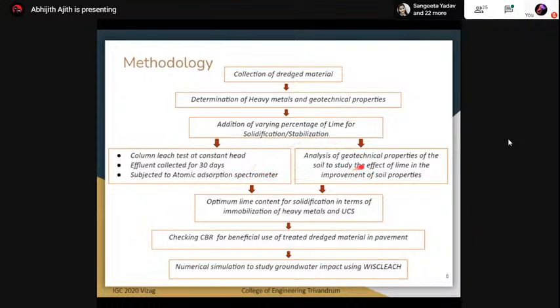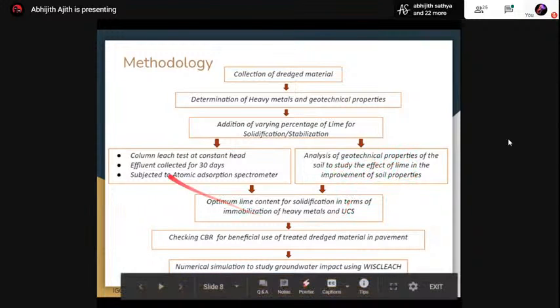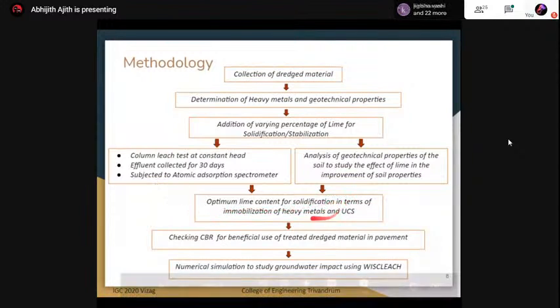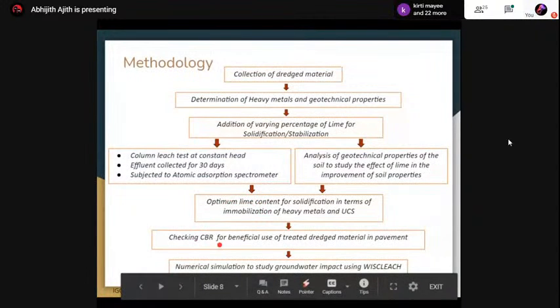On the other hand, the strength and compaction characteristics of the soil on the addition of lime were also analyzed. So based on the UCS value and the immobilization efficiency calculated from the column leach test, an optimum lime content was found. For this optimized sample, CBR was checked just to make sure that it could be beneficially used as a treated dredged material in pavement. In the end, numerical simulation to study the groundwater impact was done using a software called WISCLEACH, which is based on the advection-dispersion-reaction equation.